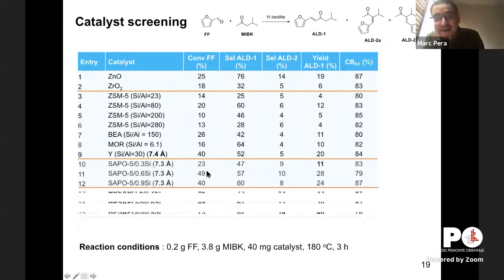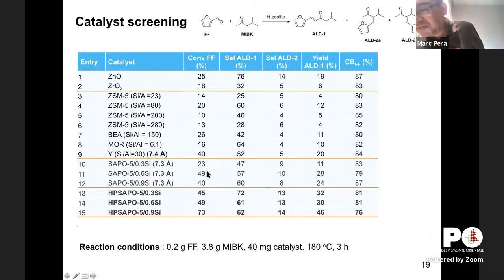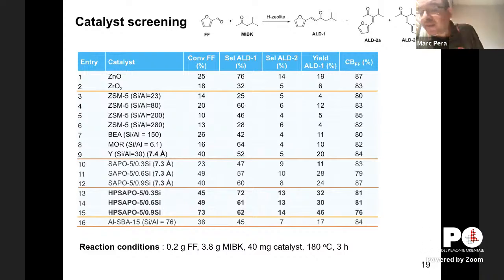But if you make this hierarchical now, the situation changes. So the pore aperture is important, but also the fact that you have mesopores in the system, you can increase really the catalytic activity. When we compare this to a standard, just a benchmark catalyst, SBA 15 catalyst, only mesopores, you see that the conversion is lower. So it seems that this hierarchical structure of this SAPO material with its good pore aperture and the acidity that this solid is capable of generating could be something promising for the project.